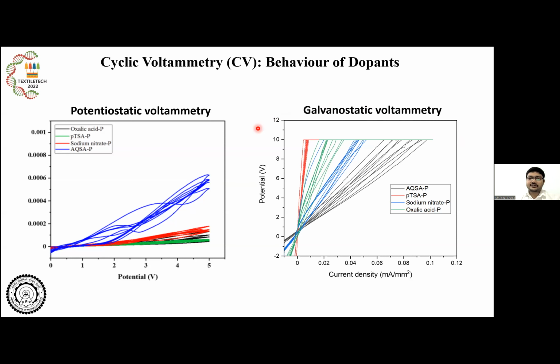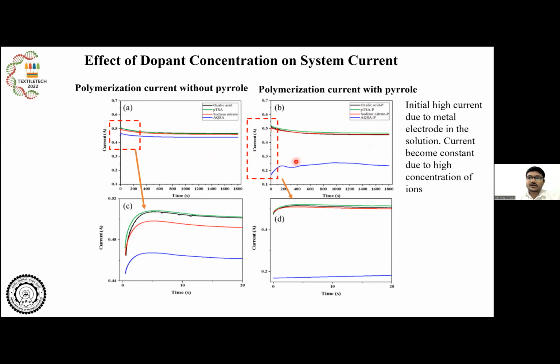So in both cases, it was observed in the 5 cycles that these compounds which are being used for the polymerization get ionized after some time. So after the ionization, these get embedded into the polymer film and then provide the desired conductivity. The method which was used for polymerization is also known as chronoamperometry, where a constant potential is applied for the desired time. We have done the process for 30 minutes, which is around 1800 seconds.